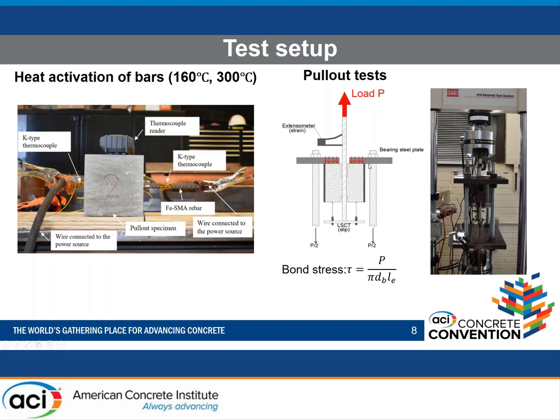And the connection between the top plate and the bottom plate, this one and this one, was achieved with 4 rods, which I'm showing here. So this is for your convenience. You can see the force, the bearing stresses, and the reaction forces from the rod. Of course, from equilibrium, we can compute the bond stress from the force that the machine has generated during the test, depending on the bar diameter and the bonded lengths.